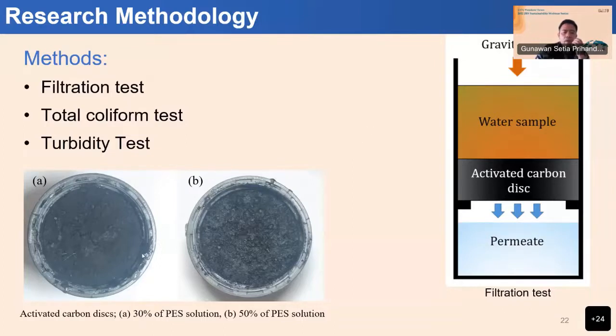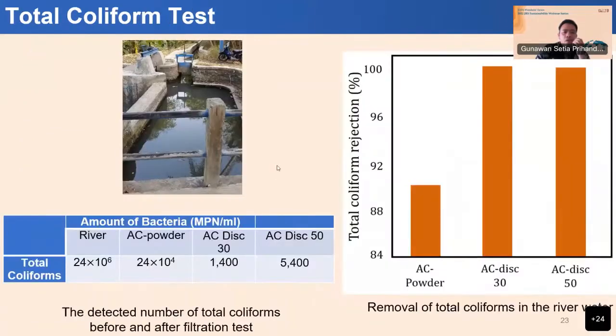Okay, so for this purpose, we have a 30% PES solution compared to the activated carbon powder, 30%, and also a 50% solution. And then for the coliform test, we collect the water sample from the river. This river is used for the irrigation system in Yogyakarta, Indonesia. So it's completely very dirty, and there are so many coliform bacteria here.